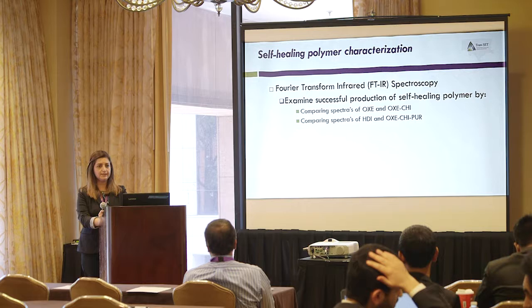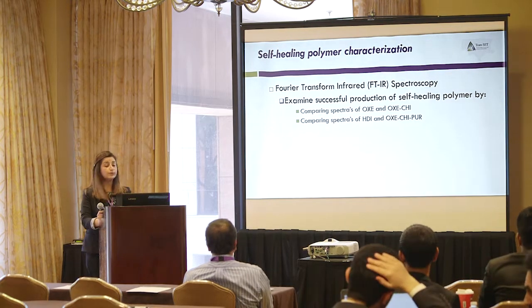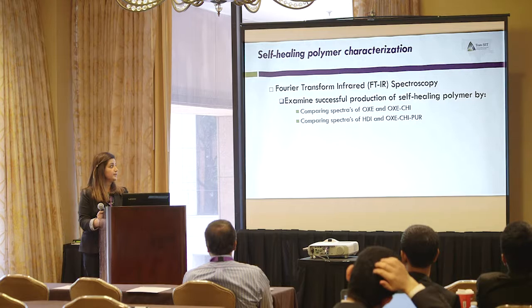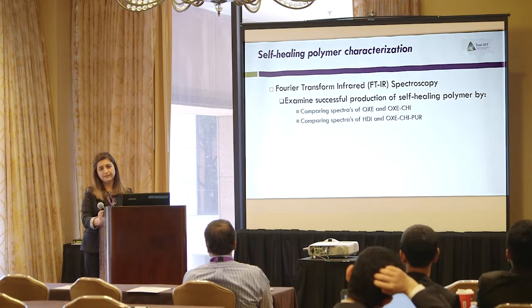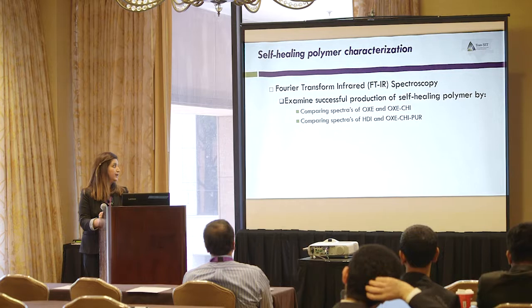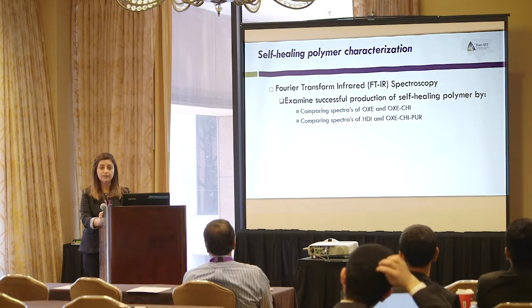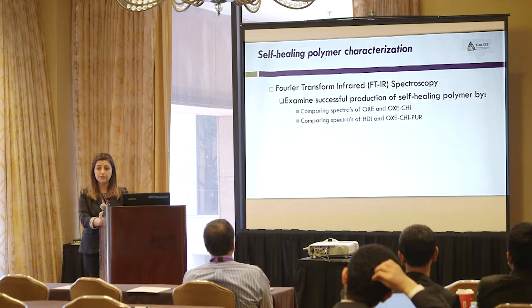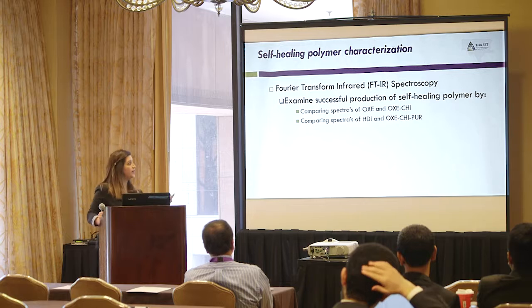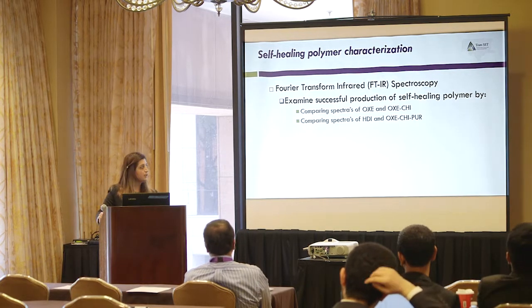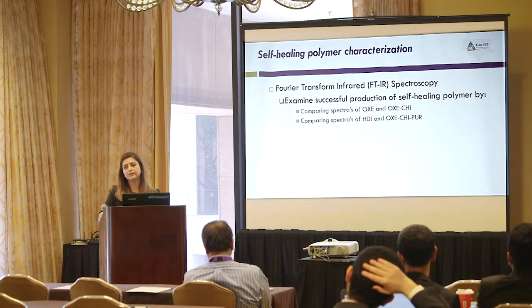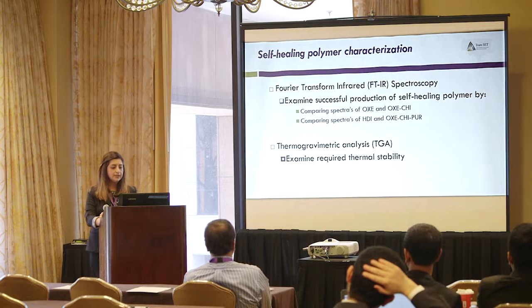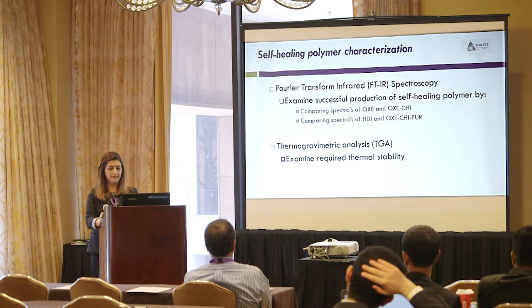After we produce this self-healing polymer in our laboratory, we need to use FTIR spectroscopy to confirm successful production of the self-healing polymer. We are going to compare the spectra of oxime with the spectra of oxime-substituted chitosan, and then we're going to compare the spectra of HDI, which is an isocyanate, with the spectra of the final material, which is the oxime-substituted chitosan polyurethane. And then we're going to use thermogravimetric analysis to measure the thermal stability of the self-healing polymer.